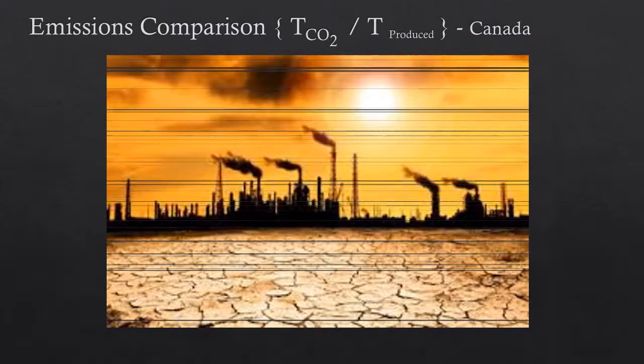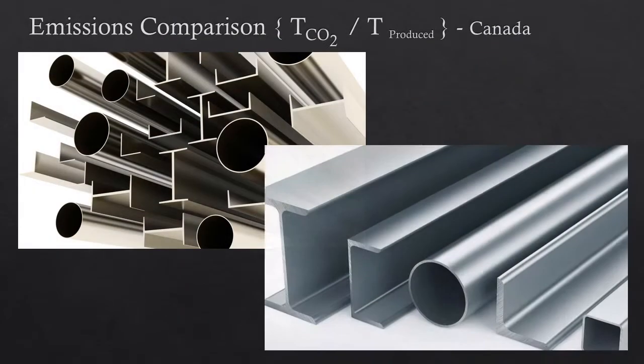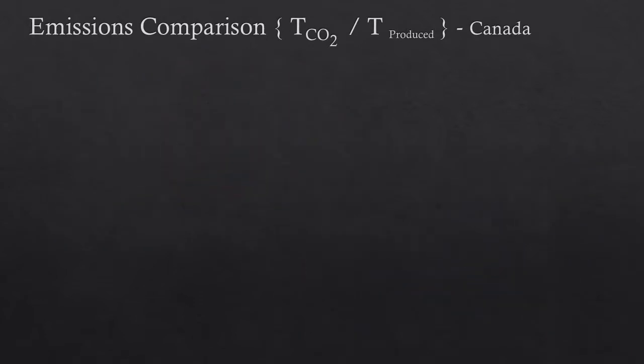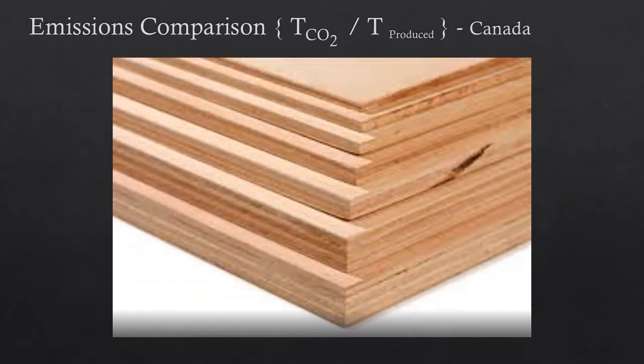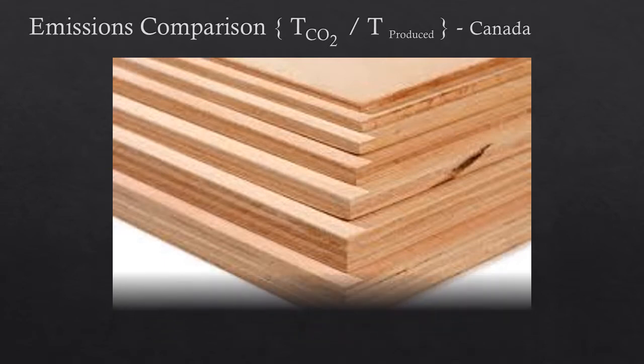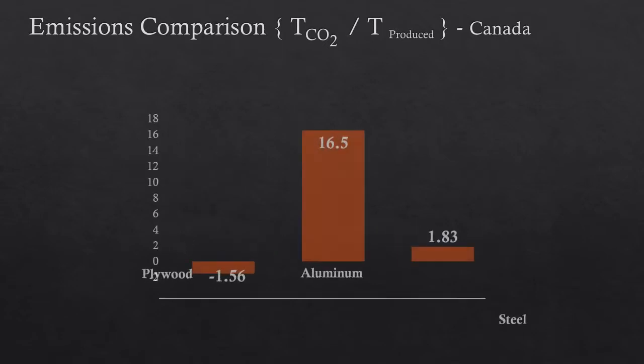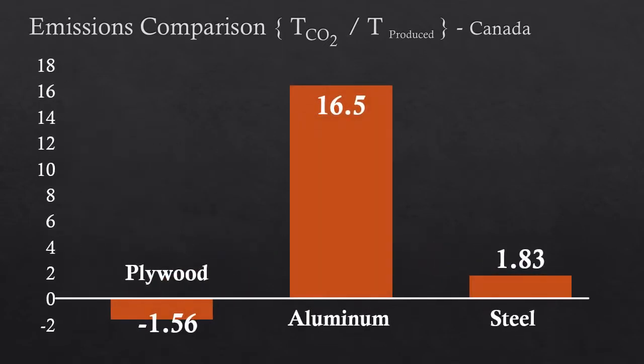While the production of this material will have an impact on the environment, its effect needs to be compared to that of other materials used for the same applications, namely steel and aluminum. Because densified wood is not in mainstream production yet, plywood was selected for the comparison, as the processes to make it are similar to that of densified wood. Carbon emissions due to the production of plywood produced in Canada are negative 1.56 tons of CO2 per ton of plywood. This value is negative due to the net positive processes that happen in the industry in which CO2 emissions are sequestered during production.